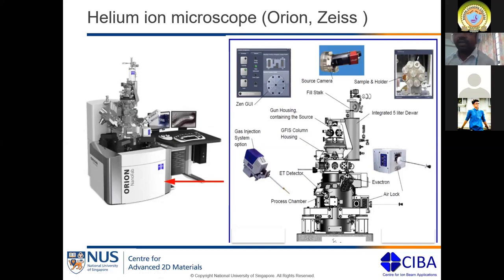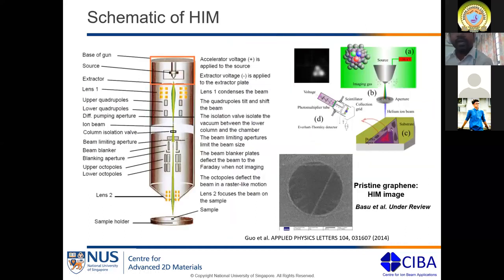If you look at the internal part of the helium ion microscope, you can see here the top part is the gun where you have the source, and from the source you generate the ion beam at a particular condition, and then it goes to a set of electromagnetic lenses or quadrupole lenses. Then you have different beam optics, and then you let it fall on your sample, and from that specimen, you detect the secondary electrons which are emitted because of this ion interaction.